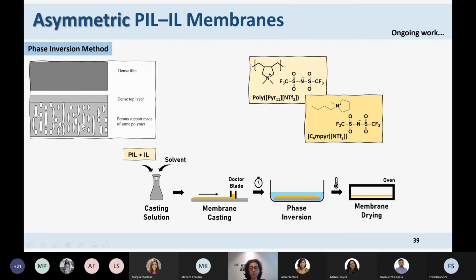Let me tell you that this has already been done for a couple of electrolytes and other polymers for membrane separations, but typically liquid-liquid separations, not gas separations. So we are using the same polymers that we used before, and we just do our casting as we would to prepare dense films, and then we let it evaporate for a very short period of time so that we create our top dense layer. And then we put it inside of the non-solvent to take out all the solvent that we have inside. And then we just put the membrane in an oven to dry.